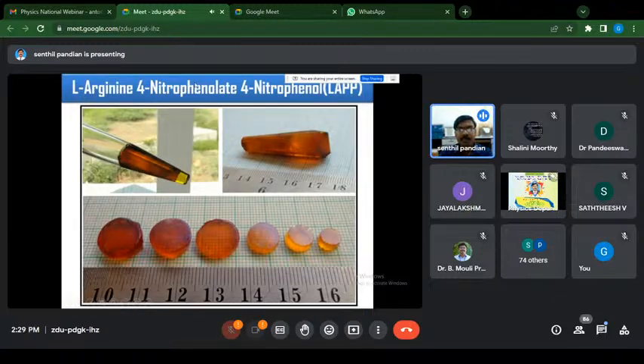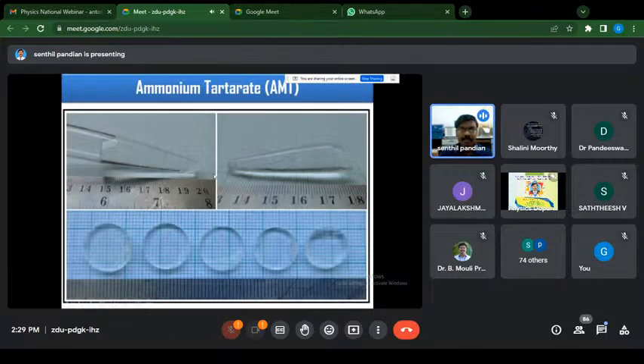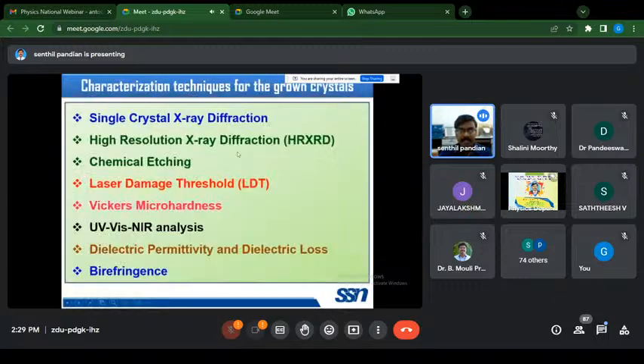And this is the L-arginine 4-nitrophenolate 4-nitrophenol derivative single crystal grown by the SR method. This is the ammonium tartrate single crystal as grown with the glass sample, and this is without the glass sample, and these are the cut and polished wafers.